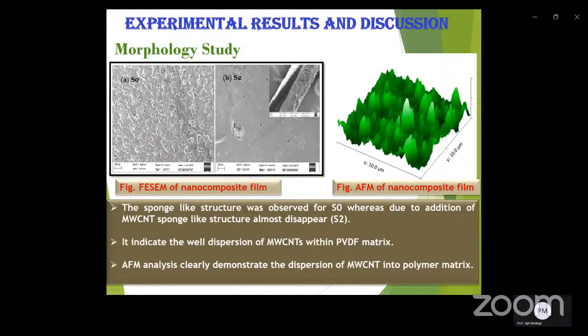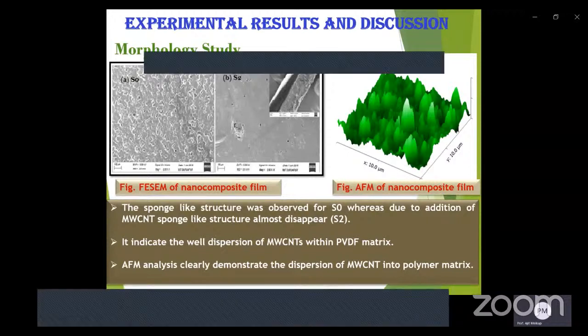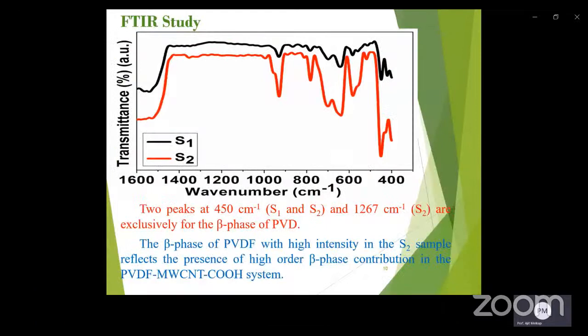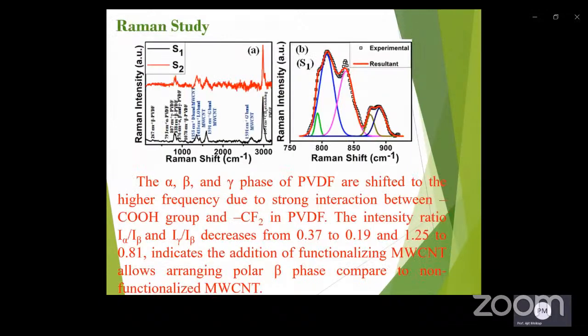Morphology of the films is described here. The sponge-like structure has been observed for pure PVDF, whereas due to addition of MWCNT, the sponge-like structure almost disappears. AFM analysis clearly demonstrates the dispersion of MWCNT into the polymer matrix. The analysis of the FTIR peak suggests the existence of the alpha, beta, and gamma phases of the film. The beta phase of the PVDF with high intensity in the S2 sample reflects the presence of a high order beta phase contribution in the PVDF MWCNT system.